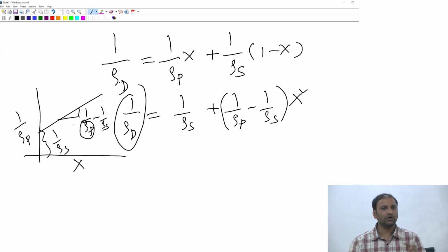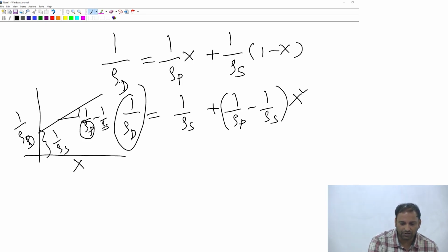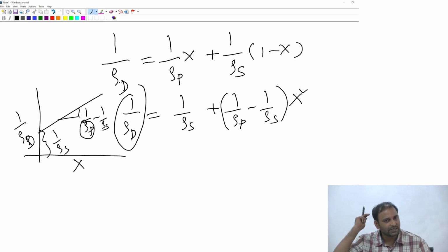What is being done is that you prepare a series of dispersions, 5 or 6 samples. I know the mass fraction of particles in each dispersion. I measure the density of each of these stable dispersions, and I plot 1 over rho of dispersion as a function of mass fraction. Just by measuring the slope and the intercept, I can calculate the density.